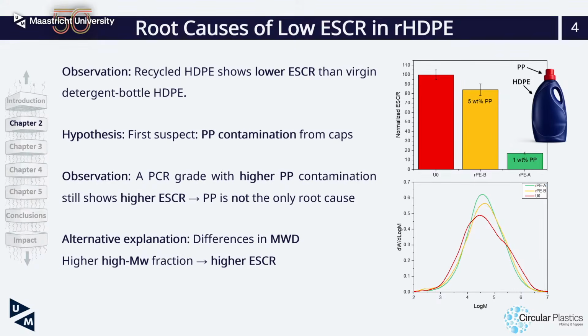When we check the differences in molecular weight distribution, we see a difference. Usually, and based on literature, we know that materials with a larger high molecular weight fraction tend to show higher ESCR. This suggests that the reason behind the ESCR loss in recyclates is not only PP contamination, but also something coming from differences in molecular weight distribution.